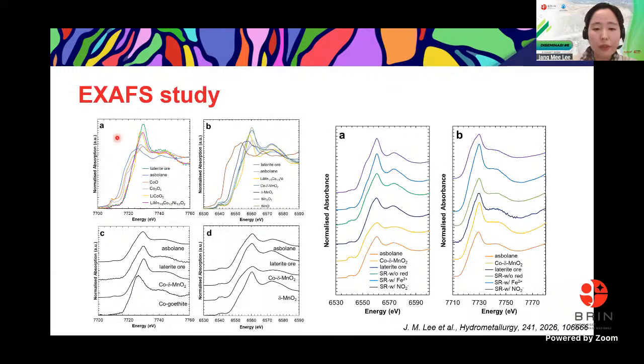Yeah, this is the cobalt K-edge, and this is the manganese K-edge spectra. And this is also the solid residue, SR. Let me explain the left side first. The left side is about the initial laterite ore, and we compare it with reference materials with different oxidation states. As you can see here, in the case of cobalt, the laterite ore shows a position pretty similar to the 3+ oxidation state, lithium cobalt oxide. This indicates that the main oxidation state of cobalt in the laterite ore is 3+.